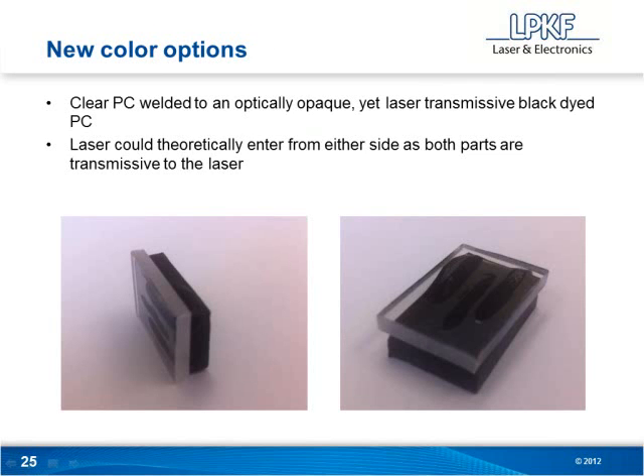This is actually a test that we ran. Tony, I believe you guys ran this one in your lab, but what we're looking at here is a clear to black, and why this is interesting is because that lower black layer, although it is black, it is actually transmissive to the laser. So any laser you shine on this black part would pass right through it, except for the higher wavelength lasers will get some absorption. It's dyed black rather than filled with carbon pigment, and that allows laser to pass through it.